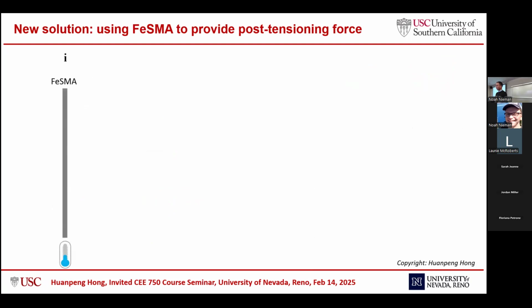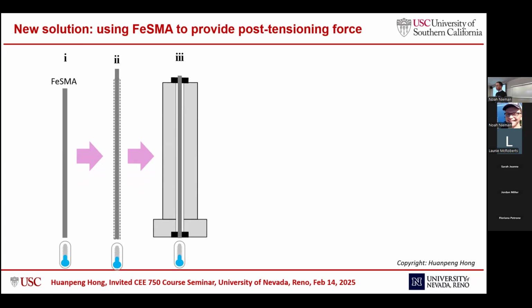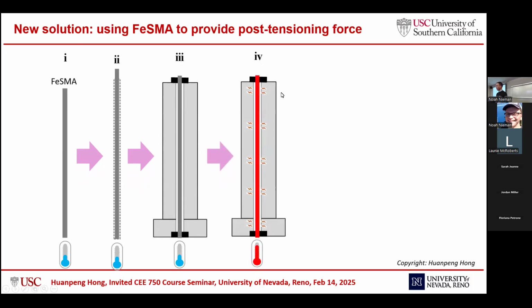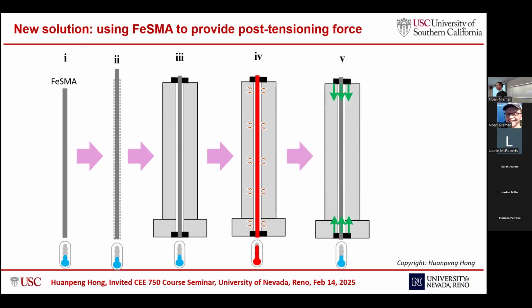So here comes the shape memory alloy. If we use iron shape memory alloys, this problem can be solved. It starts from the original shape. We stretch it to some deformation, and the first two steps we can do in a factory or in a laboratory. We can use the heavy hydraulic devices, but they are not needed on site. And then we can put this stretched iron SMA into the column. Here comes the on-site construction. We just put this tendon in the column, and then apply some heat stimulation. It can be either electric resistance heating or some kind of heating tip, and recovery stress, or a post-tensioning force, will be generated inside the material. So that means for the on-site construction, there's no hydraulic device needed at all.